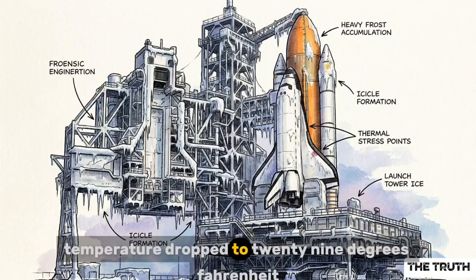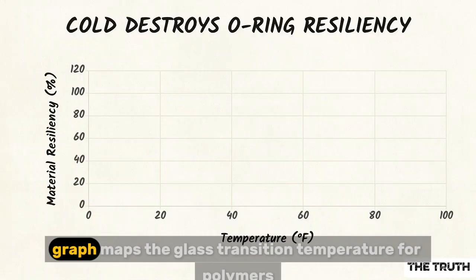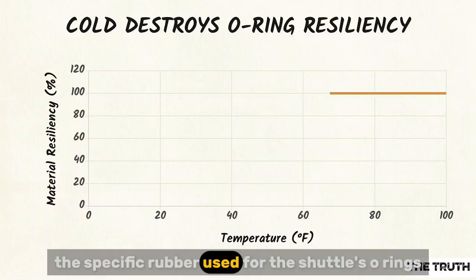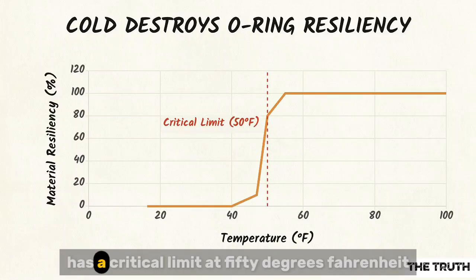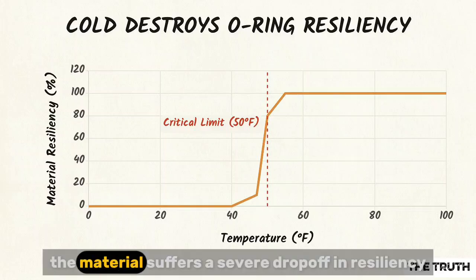On the morning of January 28, 1986, the launch site temperature dropped to 29 degrees Fahrenheit, 15 degrees lower than any previous shuttle launch. This line graph maps the glass transition temperature for polymers. The specific rubber used for the shuttle's O-rings has a critical limit at 50 degrees Fahrenheit. Below this mark, the material suffers a severe drop-off in resiliency.